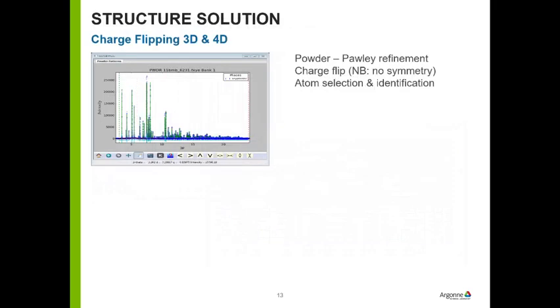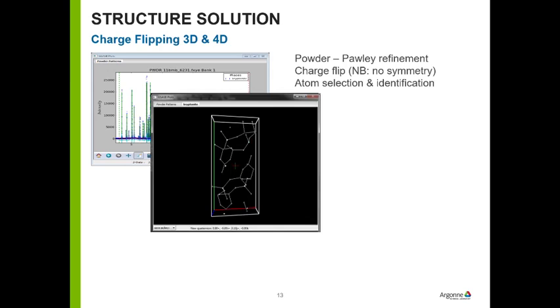And so if you do structure solution, GSAS-II does this by charge flipping. So you start with a pattern, you do some sort of intensity extraction, you do the charge flipping, and you wind up with a set of atom positions, which, by the way, a charge flip result has no reference to a space group or anything else like that. The origin is completely arbitrary. And so I use a sort of trick involving phase relationships in the space group to try to shift the origin over to where it belongs, but it could still be off, so you may have to shift it.